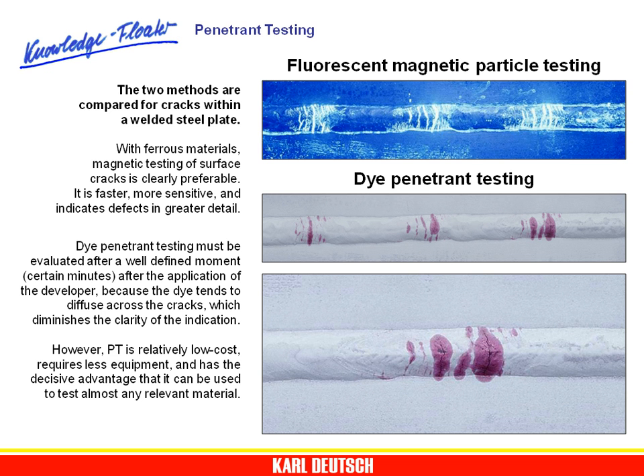Dye penetrant testing must be evaluated after a well-defined moment, certain minutes after the application of the developer, because the dye tends to diffuse across the cracks, which diminishes the clarity of the indication. However, penetrant testing is relatively low cost, requires less equipment, and has the decisive advantage that it can be used to test almost every relevant material.